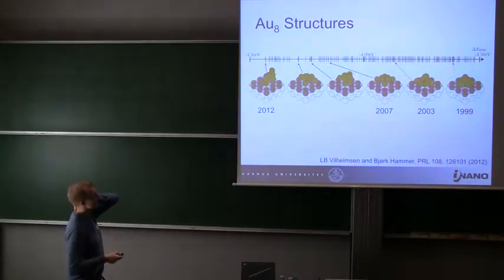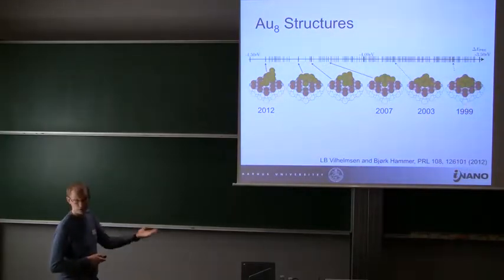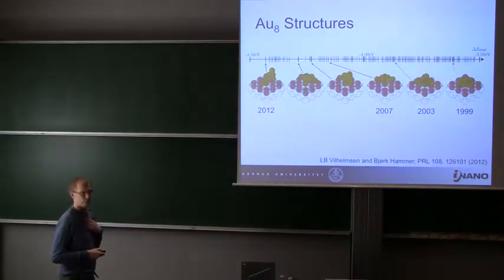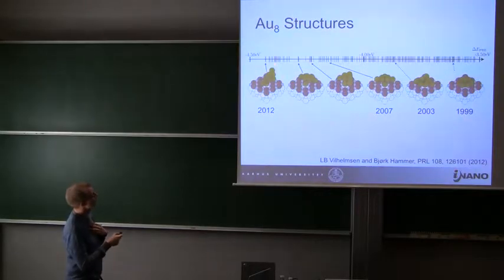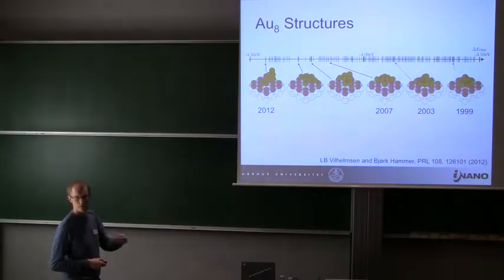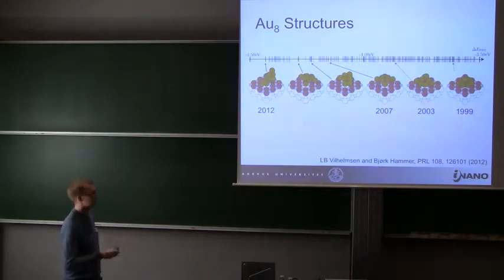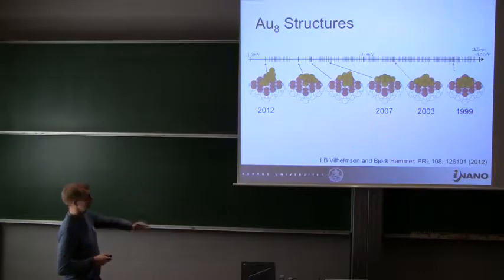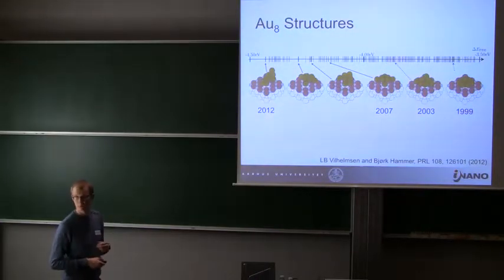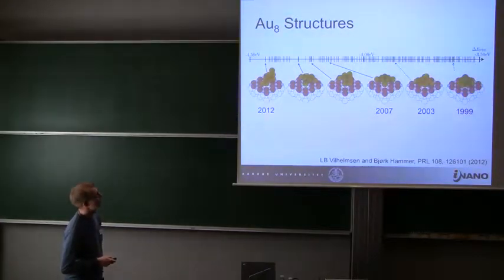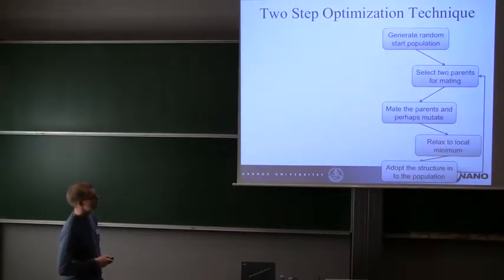We can plot an energy axis. Up here each vertical gray line indicates a local minimum. Here I put in the three structures from the literature. You see they are all over the place. This was the two proposed as the global minimum, but the structure you see that I found is more stable. I've done this with PBE. I have also done this with the M06L functional instead, which better describes gold. With PBE there's a vertical structure pointing upwards, but that's because PBE has problems with gold and the interaction with the oxide. Actually it turns out to be a flat structure when using meta-GGA.